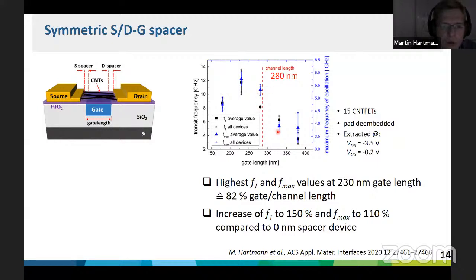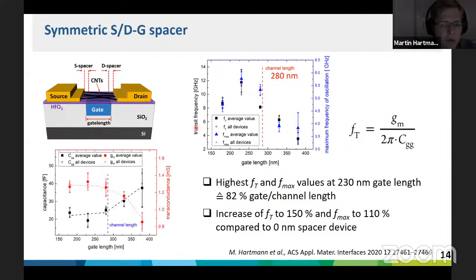And what would you also see here? If you have an overlap, so some additional parasitic capacitances, then the frequency drops quite strongly. This is expected. The highest transit frequency is not for the lowest spacer, but for something like a 50 nanometer spacer, which corresponds to a gate length of 80% of the channel length. There we saw the highest transit frequency and the highest frequency of oscillation. For smaller or bigger gate length, the speed was again reduced.